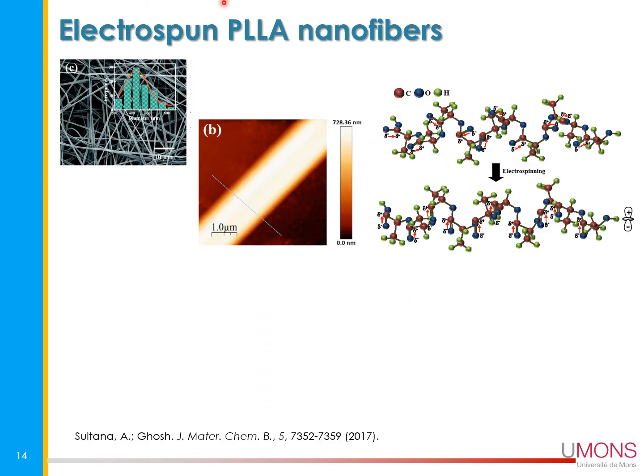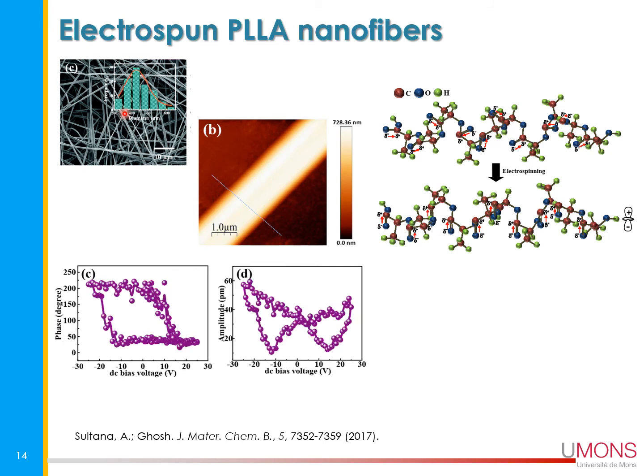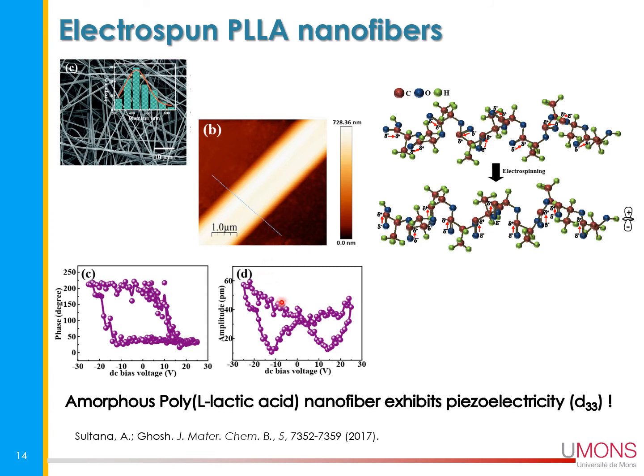As we saw before, and because the subject of this talk will be about PLLA, polylactic acid nanofibers, we saw in a paper from Sultana that in fact electrospun nanofibers can present some piezoelectric properties. This is the typical shape that we will see later, the hysteresis curve or butterfly shape, by applying a voltage, and you can measure the amplitude or the phase, and out of that it's possible to derive the piezoelectric constant. So even if PLLA is known to present some polarization under shear force, it appears that for amorphous polylactic nanofibers, thanks to the electrospinning, you can present the d33. So with this kind of electrospun PLLA nanofiber, it's possible to measure those coefficients with scanning probe microscopy as we saw before.